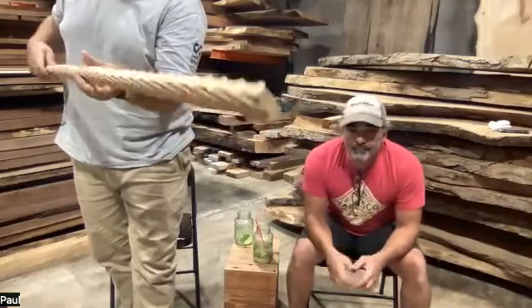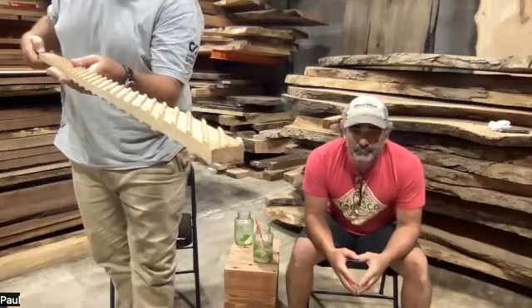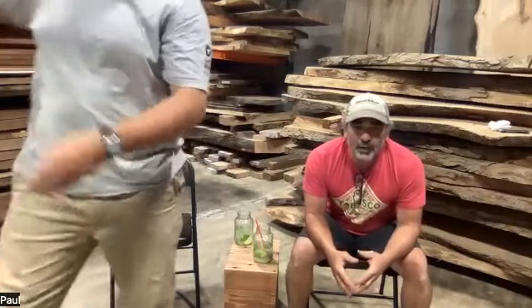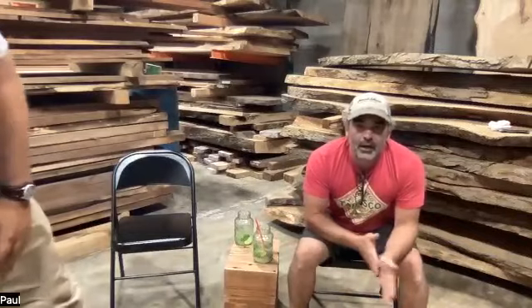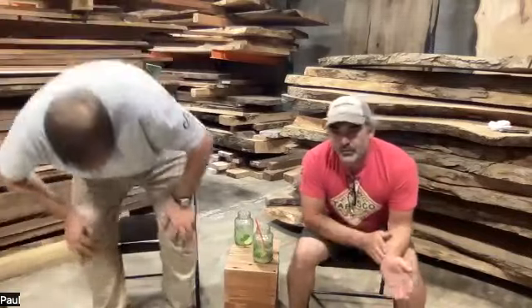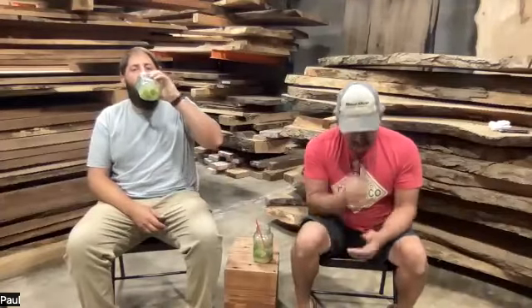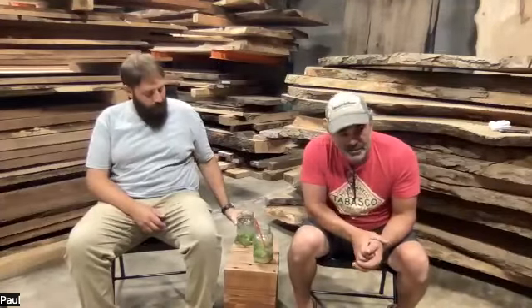So we're not leaving anything on the slab, which a lot of people call sticker shadow. I was going to say, for a while we were using the same material. If we were cutting a log, we would cut the stickers for that log out of the same material and then stack or sticker it up, and still had problems with sticker shadow. We tried dissimilar materials. We tried kiln dry materials. We tried pretty much everything until we came across these, and these have eliminated sticker shadow. We have not had it since we started using them.